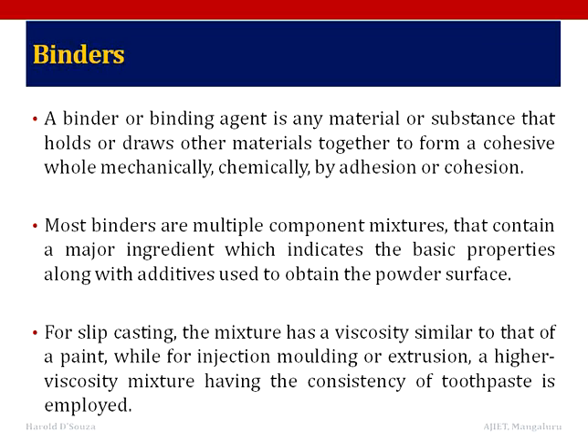As a primary requirement for easy shaping, the binder must wet the powder surface. So, various chemicals are employed to improve the wetting between the powders and the binder. Now, for ferrous alloys, the most common coupling chemicals are stearates, including stearic acid, zinc stearate, and ethylene bisstearamide. Of these, stearic acid is a low cost polar molecule having a density of 0.85 gram per centimeter cube and a melting temperature of 65 to 75 degrees centigrade.